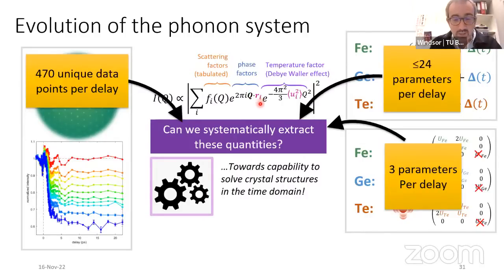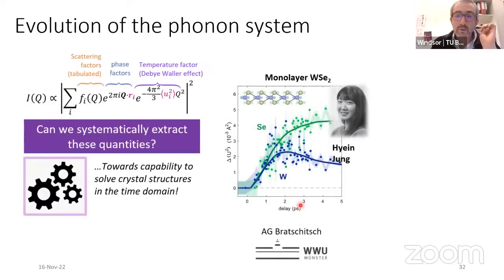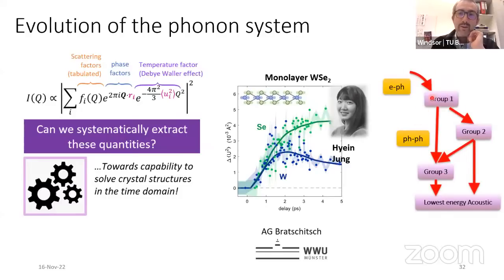Now, I'm not going to show you this result for FGT yet, but we have done this on a number of similar systems, most recently and soon to be published on a TMDC monolayer. So this is a monolayer from the group of Professor Bratschitsch in the University of Munster, done by our student Hyein Jung. And what you can see here is a monolayer of tungsten diselenide. This is a cartoon shown here. And you can see that the incoherent oscillations of the selenium atoms follow a different path than that of tungsten. So we have an initial rise in phonon population, which affects the vibrations of both selenium and tungsten, followed by a change in trend. There's sort of a next phase in the phonon-phonon relaxation process. When you imagine a kind of picture like this, we have an initial growth here, followed by different phonon-phonon relaxation processes here. So we know that this technique can in principle work, and that's the direction we're going towards.